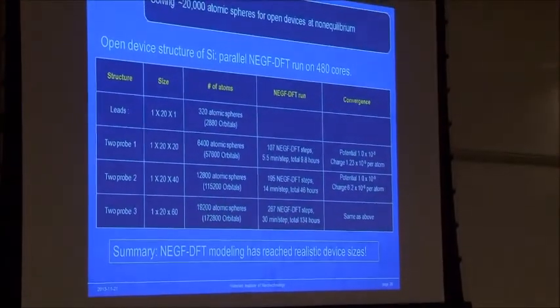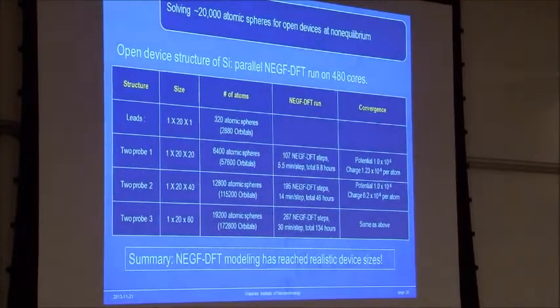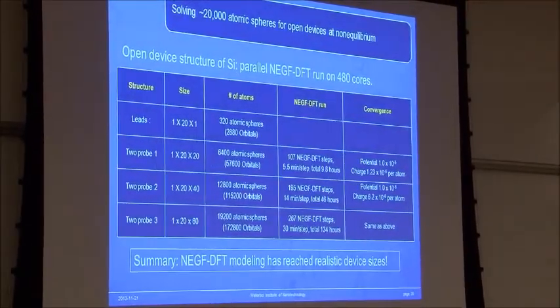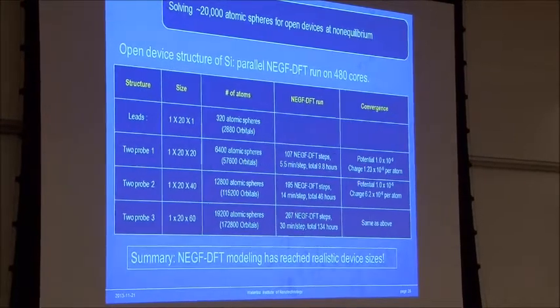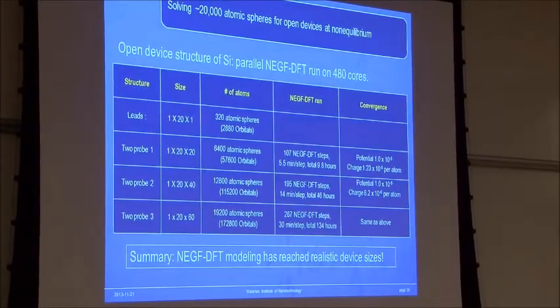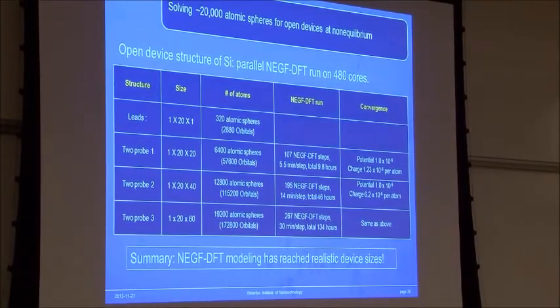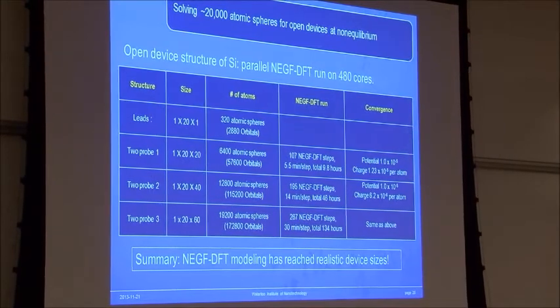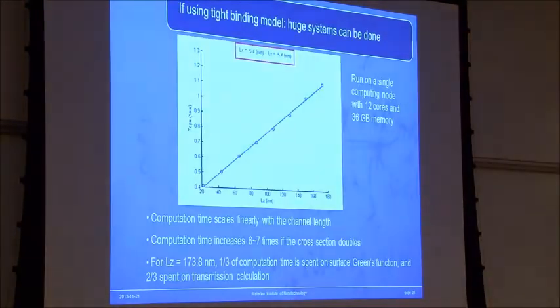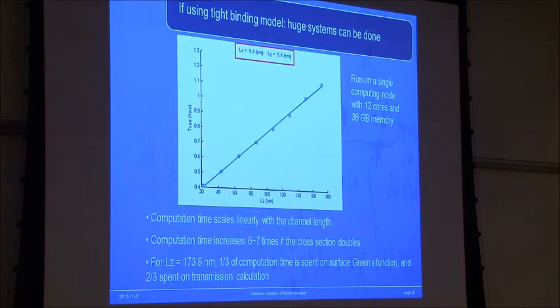For a device simulation, the largest we have done is about 20,000 atoms. This is for silicon, with 10 orbitals per silicon, and we can converge this result in about several days. So we are now working very hard to reduce the computation and see whether we can make this an easily used engineering research tool.